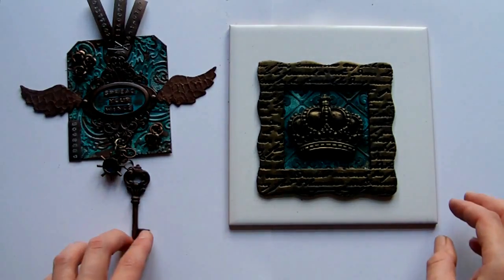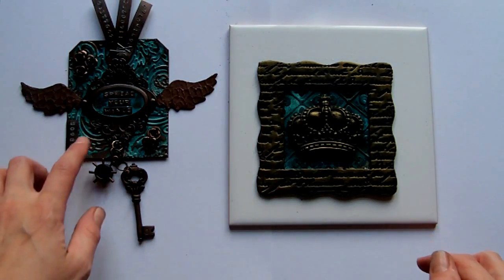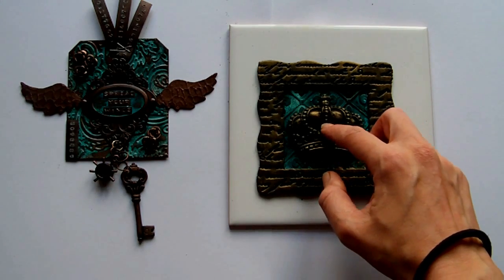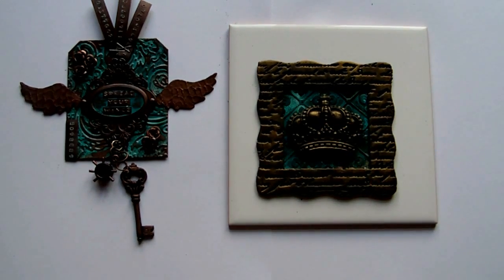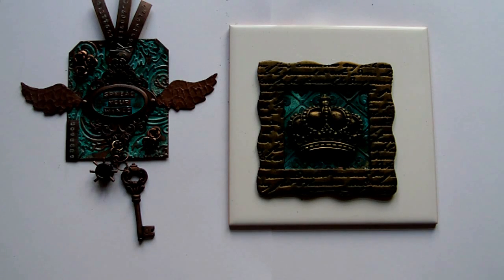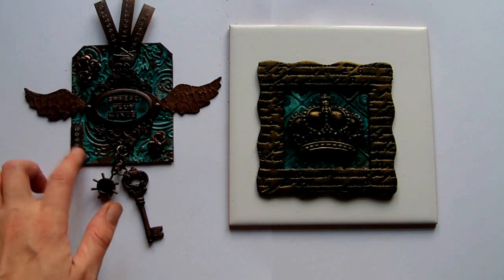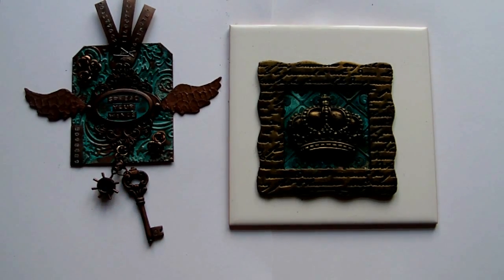Things that I did learn while doing the projects: the patina does come off a little bit. I added some spray fixative to it which helped a little bit. And if you're trying to glue things onto it, you really need to sand that surface in the area where you're going to glue embellishments down, otherwise the patina just flakes off and there's nothing for the adhesive to hold on to. I hope you like those and I hope you give the aged metal a try — thanks for watching!